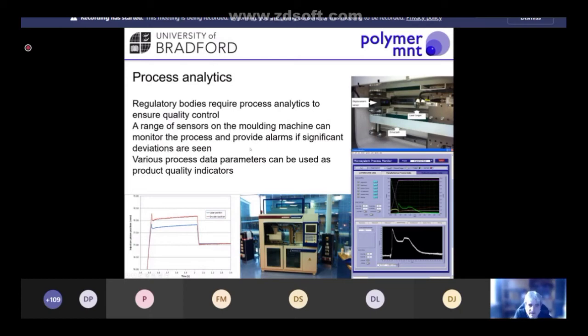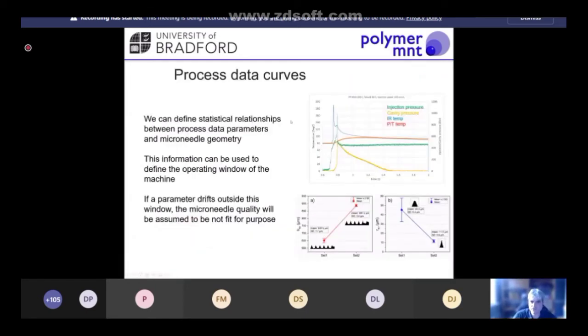And what we can do is provide alarms if we see significant deviations in any of these measurements from cycle to cycle, that could indicate that something has failed in the process, or we have problems with our raw materials, or something that could affect the overall quality of the part. So we can use these aspects of our manufacturing process as product quality indicators. On the right here, I have an example of some of the process data that we can collect from the injection molding process. So we have injection pressures. You can see the green line here is our injection pressure. This gradually increases as our cavity fills, and then we get a peak just before the cavity fills completely.